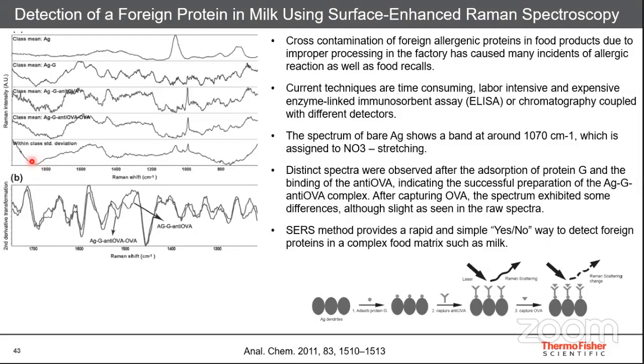So you can see the study here. These are the silver nanoparticles that have been formed. These silver dendrites are formed from a nitrate solution, so you can see an NO3 stretching in these samples. Now, once it reacts with the protein, there is no NO3 peak you are seeing here. So there is a change in the spectra, indicating an interaction of the silver nanoparticles, which we use for surface enhanced Raman spectroscopy, and it is now showing the spectrum of your protein.